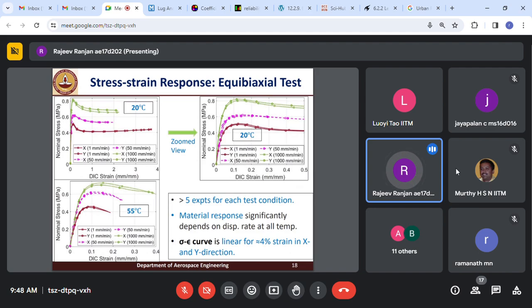This is the stress strain response for the equibiaxial test, and this plot here is the stress strain response up to failure at 20 degrees centigrade. This is the zoomed in view of this plot up to 50% strain, and this is the equibiaxial test response at 55 degrees centigrade. For each test condition, at least 5 experiments have been conducted. For both temperatures, material response was significantly dependent on displacement rate, and there was a large decrease in failure strain when temperature was increased from 20 to 55 degrees centigrade. We also observed that the stress strain response is linear up to 4% strain in both x and y directions.